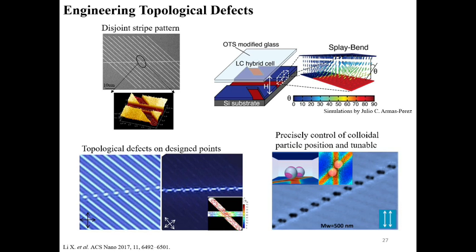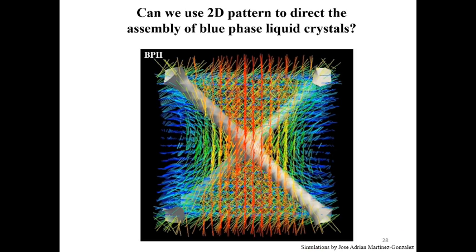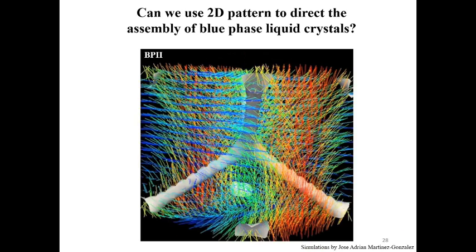And this method can create an array of pairs of those colloidal particles and bring the two particles very close to each other. That is based on the middle line you create here. The minimum separation we get is about 15 nanometers between the two particles. The particles used here are around 800 nanometers to 1 micrometer in size, and they can be as close as around 15 nanometers to each other. So with all this information, back to the more complicated three-dimensional blue phase material.